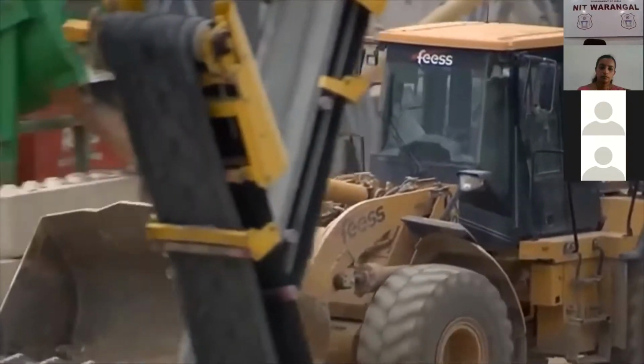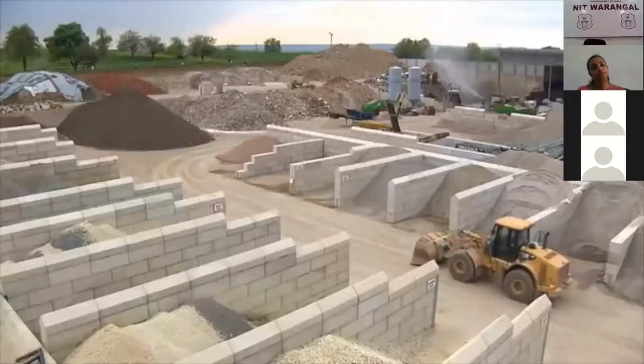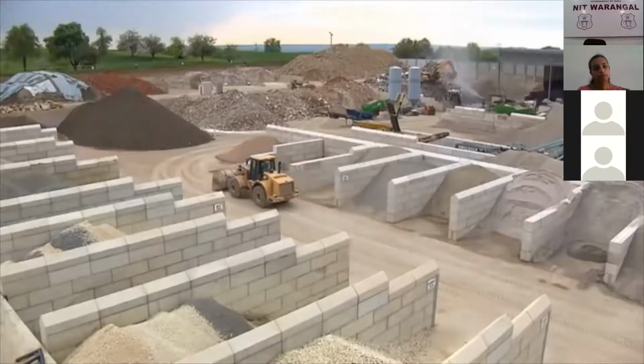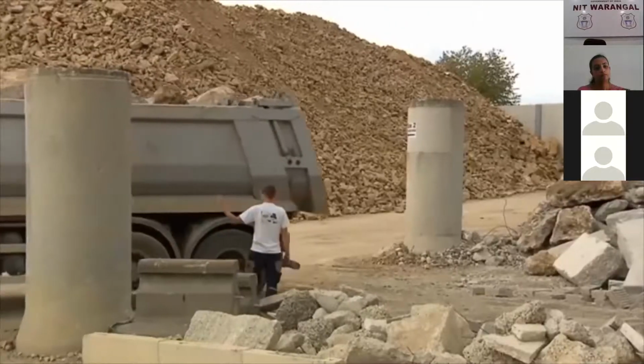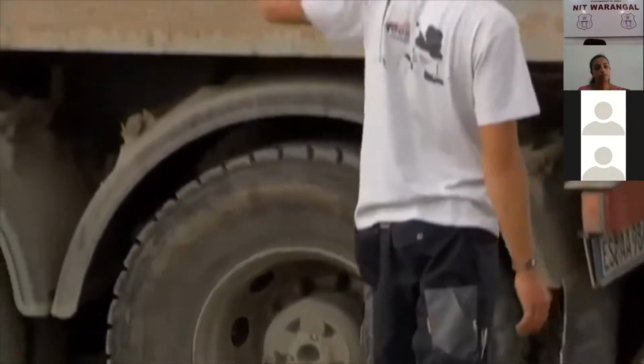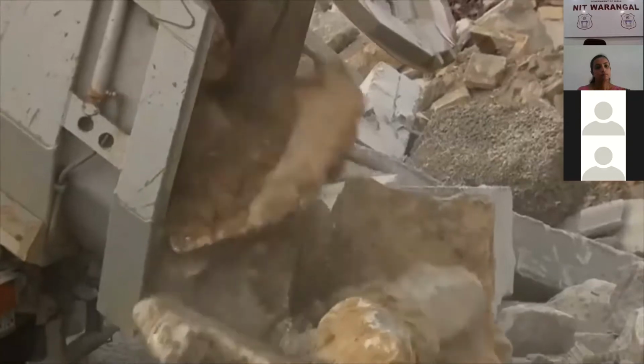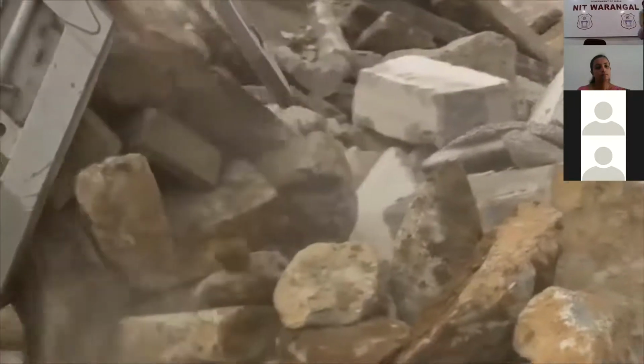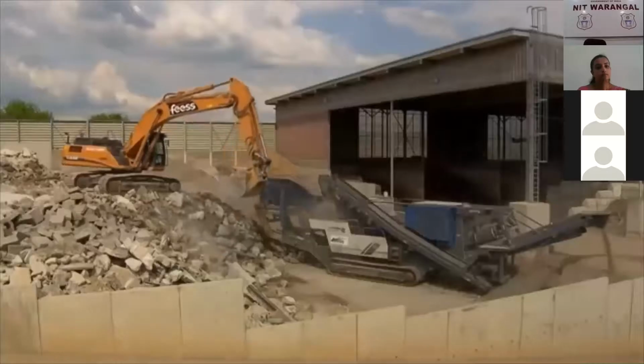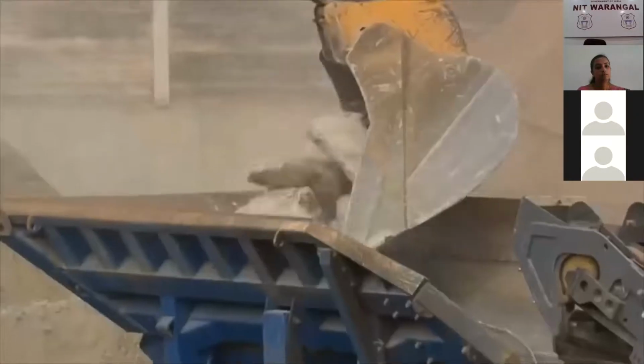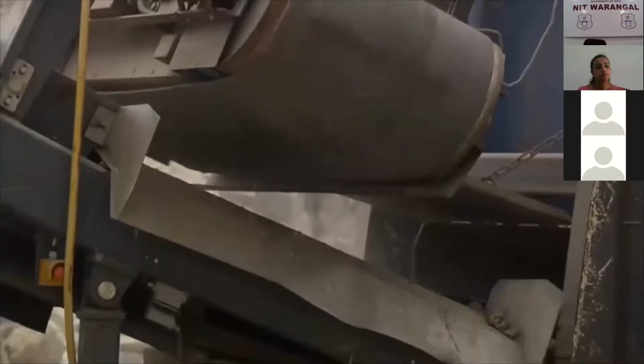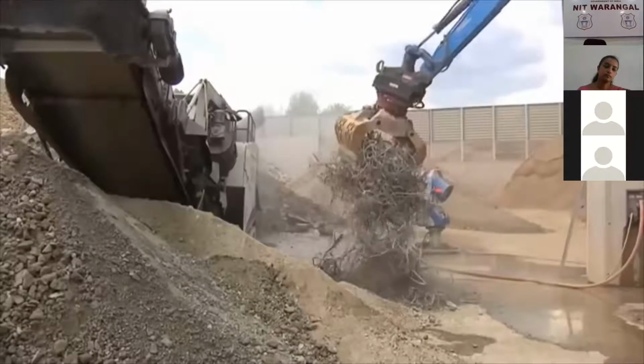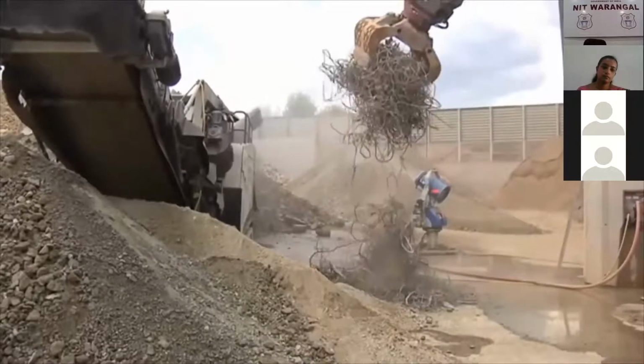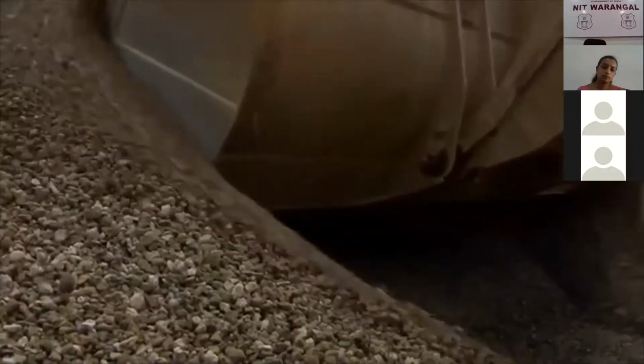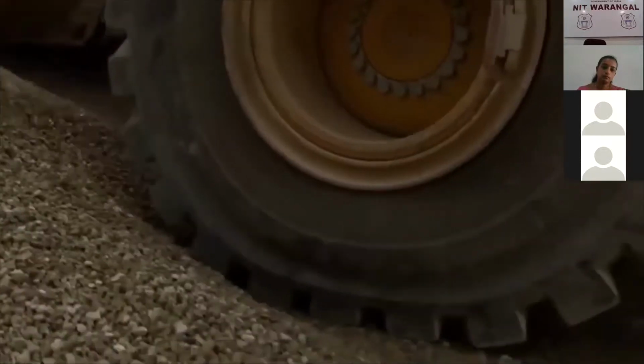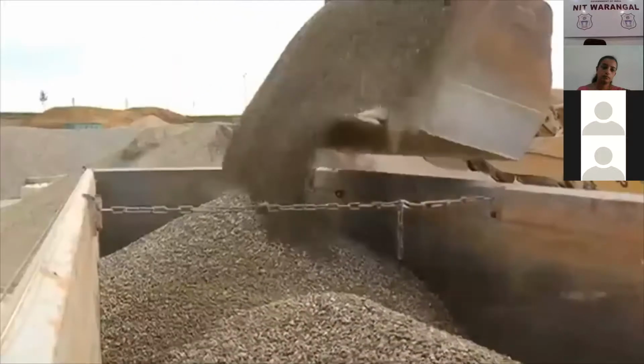The principle is put into practice at the recycling center of the Fes Erdbau Company in Kirchheim-Teck. A variety of concrete and building rubble materials are processed for reuse here, covering an area of 30,000 square meters. The rubble is collected within a radius of 15 to 20 kilometers from the recycling plant. Since the material can be sorted here according to type, only pure concrete ends up in the crusher. A magnetic belt removes the steel reinforcements. The result is a clean fraction with a size of 2 to 16 millimeters. Nearby concrete factories use this material to replace the gravel from stone quarries or gravel pits, saving natural resources.